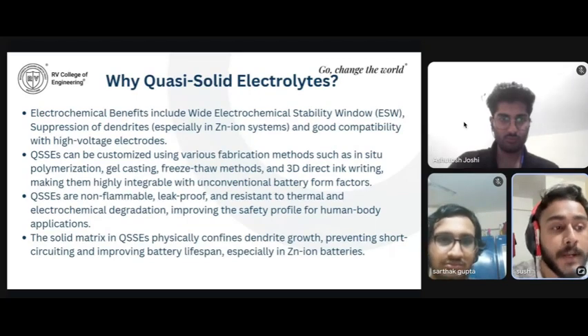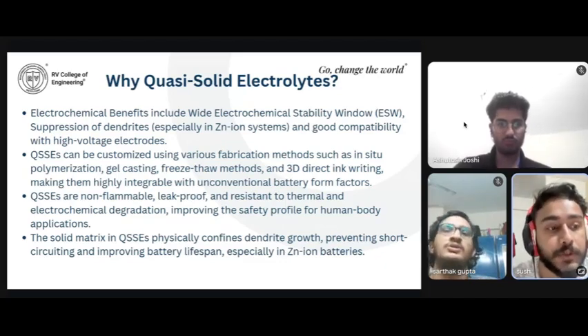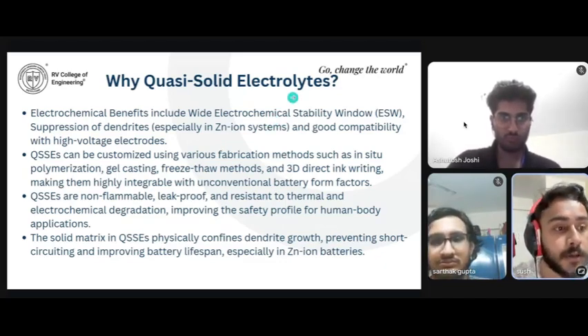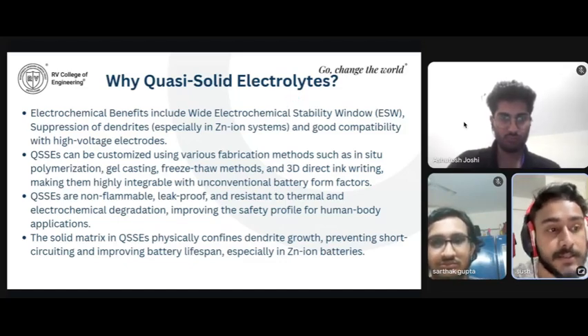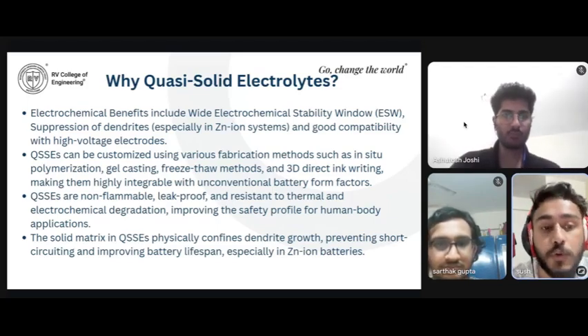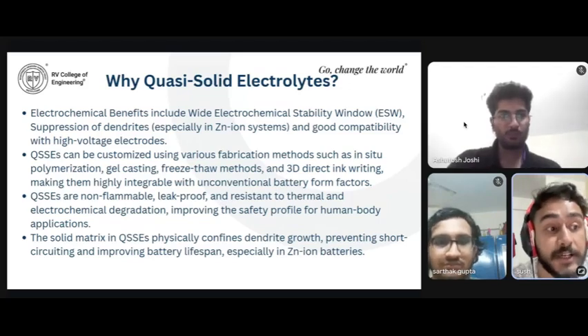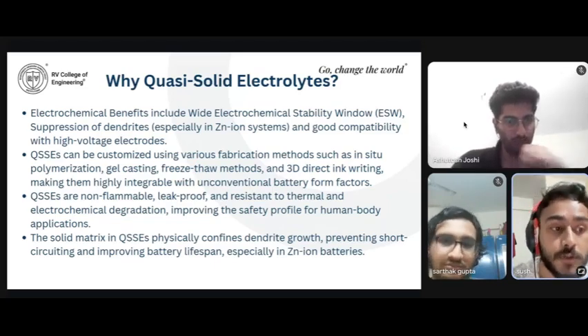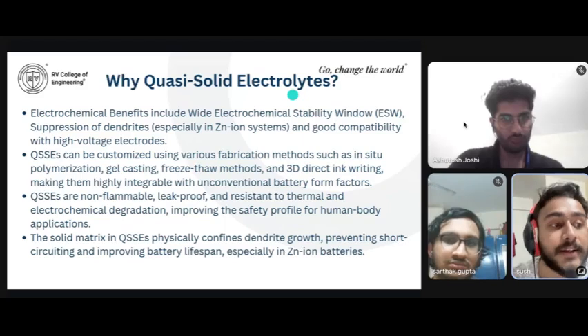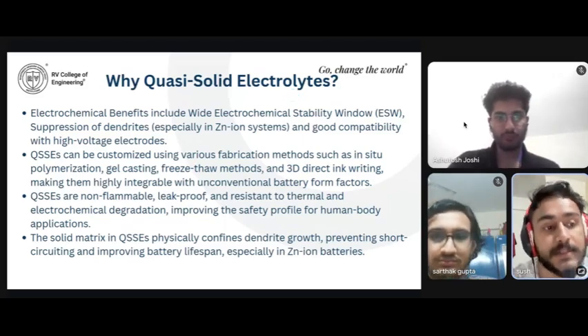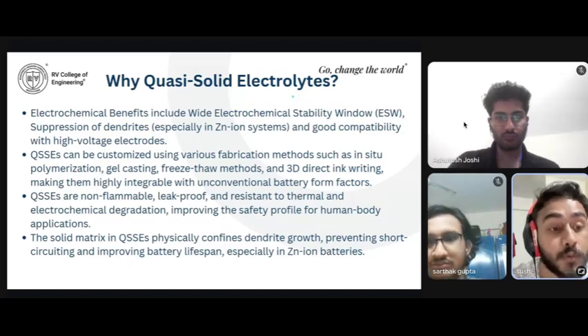So, from an electrochemical perspective, QSSEs offer several benefits. They have a wide stability window, meaning they can handle high voltages. They suppress dendrite formation, especially in zinc-ion systems. QSSEs are non-flammable, leak-proof, and resist degradation, which is great for human body applications. What's more, they can be fabricated using various methods, from in situ polymerization to gel casting. We can also do freeze-thaw methods, and even 3D direct ink writing, making them adaptable to different battery shapes and sizes. The solid matrix also plays a key role in this. It physically blocks dendrite growth, which prevents short circuits and helps extend battery lifespan. Next slide.